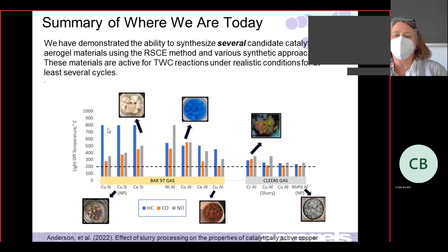Nickel alumina, cobalt alumina, ceria alumina, copper alumina. So we got pretty good with that copper alumina. And then when we went to the other gas, which is, again, a little easier to break apart the hydrocarbon, we got even better performance.